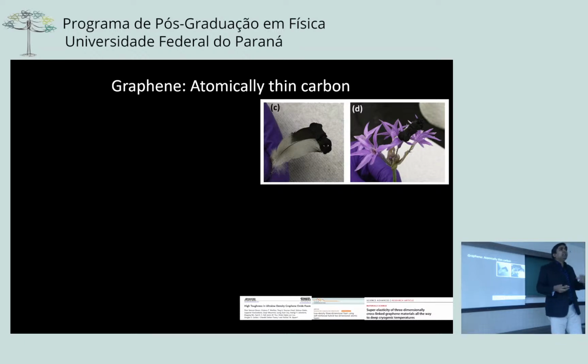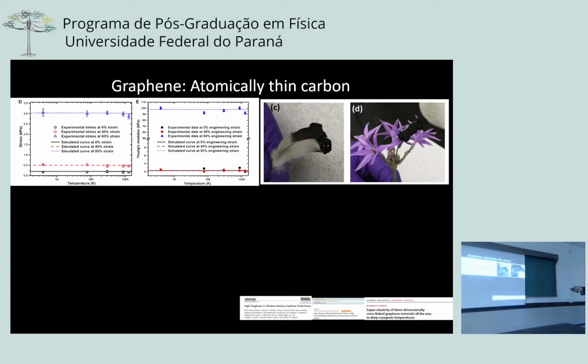For example, if you are making an aircraft which is going to land in freezing Canada, and at the same time the same material is going to work at 1100 degrees at high altitude, it becomes complicated. Now the question is, can graphene replace it? For that, the first testing was done where we make these foams, cool them using liquid helium and do a compression. So all the way from liquid helium to 1100 degrees centigrade, these foams were tested.